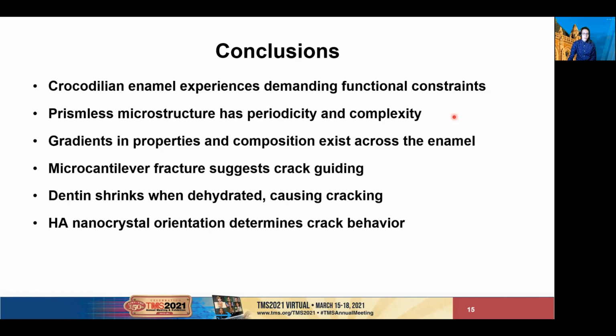The microstructure of the enamel displays some patterns and complexity that presumably have evolved to survive the extreme conditions, but they have not been comprehensively described in the literature yet. Using nanoindentation and Raman spectroscopy, we found gradients in the properties and composition, with the most dramatic changes occurring in the outermost layer of the enamel to improve the wear resistance, but overall the properties were lower than human.